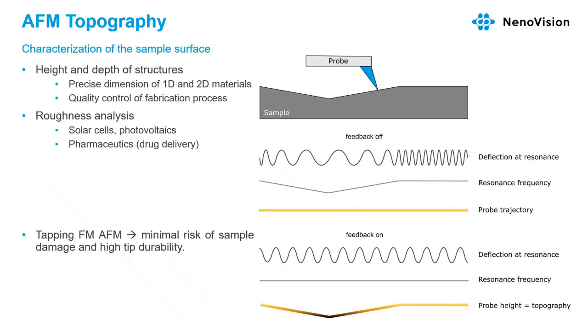We use tapping mode frequency modulated AFM, and we use Akiyama tuning fork probe to measure in the tapping mode to minimize the risk of sample and tip damage. And so we oscillate with the cantilever at its resonance with constant amplitude. But due to the topography changes, the resonance frequency changes as well. It shifts, and so if the feedback is off, the probe will go horizontally all the time, then there are some changes. And so if we use the feedback and track the frequency changes and keep the cantilever oscillating at resonance frequency, the probe needs to move, and so this movement is actually the topography of the sample.